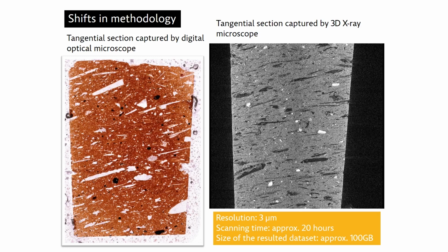Another difficulty is common to all X-ray techniques. The method is well suited to an investigation of porous structures within shards because of the high density contrast between solids and voids. On the other hand, the density contrast between a majority of non-plastic mineral particles and the clay matrix is often low, and it is difficult to visualize them clearly, especially for the purpose of quantitative analysis.